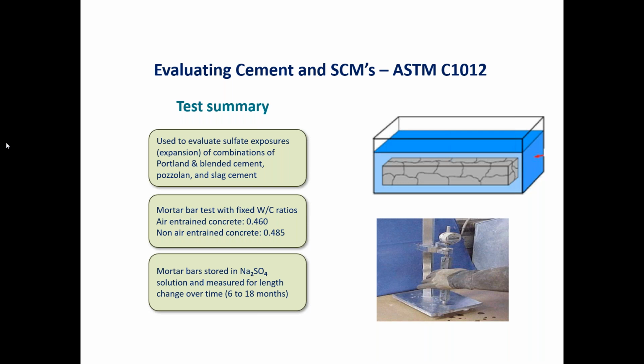Essentially, if you've produced concrete or specified concrete, you're going to specify a certain amount of maximum expansion allowed. To meet that, you're going to create mortar bar samples with various combinations of cement, blended cement, pozzolan, slag cement, microsilica, and then you're going to soak these in a solution of sulfate and measure these bars over time. Over time they actually grow, and you'll see some of that data here, and they can grow very substantially.